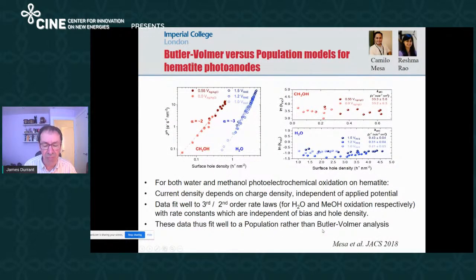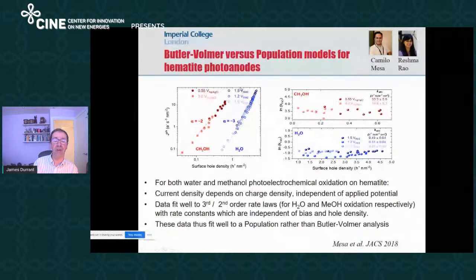Just coming back to that Butler-Volmer versus population argument, these are 2 examples of plots which indicate we are indeed in a population regime rather than a Butler-Volmer one, where the population model is appropriate. So data on the left shows measurements of the kinetics of methanol or water oxidation, or the current density for methanol or water oxidation as a function of surface hole density for different applied potentials. And what you can see is that if you normalize the data to the same surface hole density, then essentially the kinetics are independent of potential, which suggests that changes in band bending at the surface, which is the essence of the Butler-Volmer picture, are not important in terms of determining the kinetics.